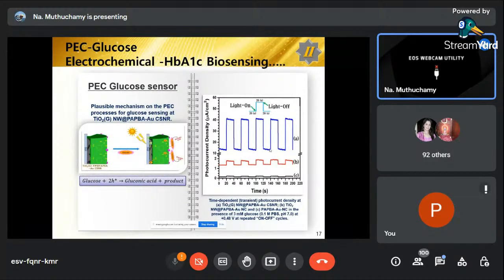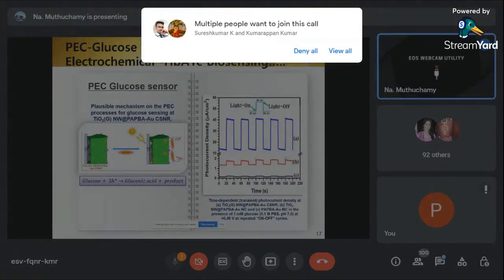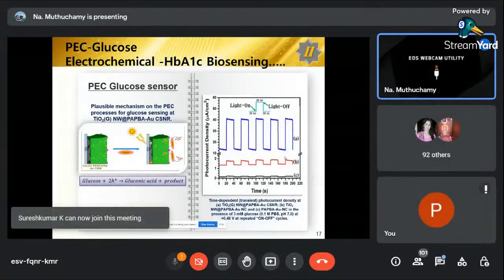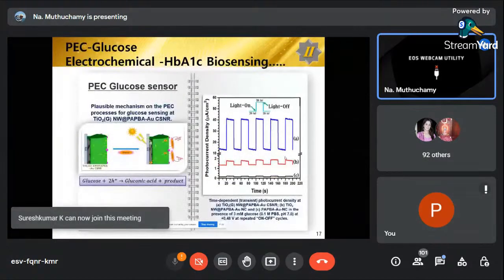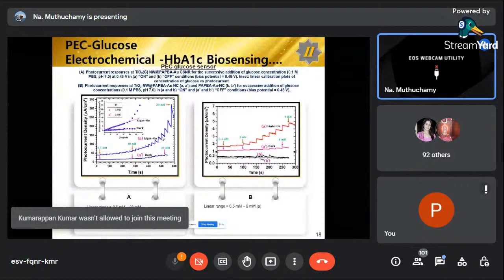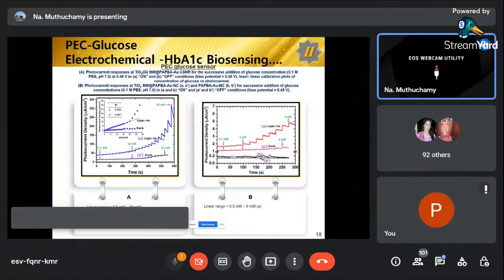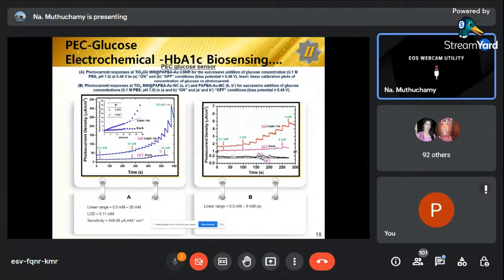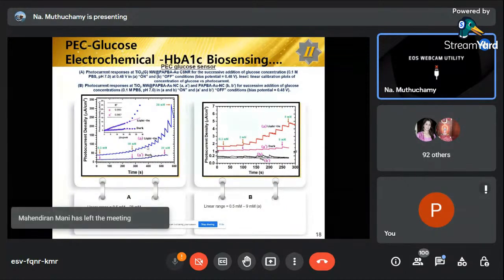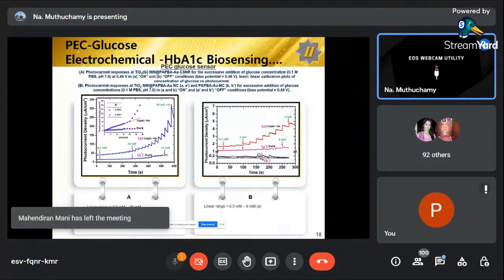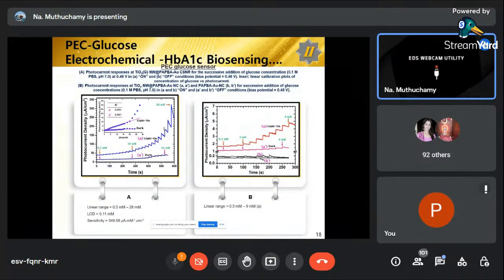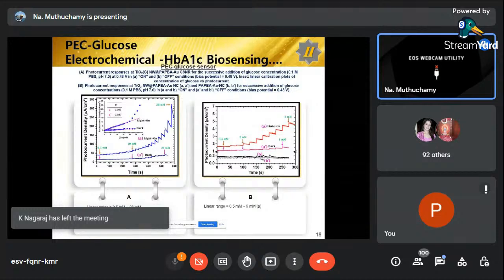I already told you the role of carbon in photoelectronic biosensors: the carbon plays a main role to enhance the conductivity. So here, due to the high conducting nature, we got that high photocurrent response. The next one is the linear range. Here we got a linear range from 0.5 to 28 millimolar. When we add the glucose molecule, the photo response current also increases step by step. Then it shows a spontaneous response, within 5 seconds we got the response.